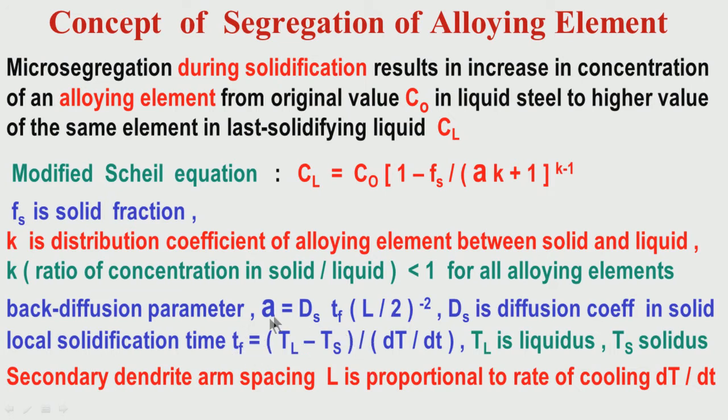It is basically the solidification temperature interval, the difference between liquidus and solidus, divided by the cooling rate, dT by dt, rate of change of temperature with time.